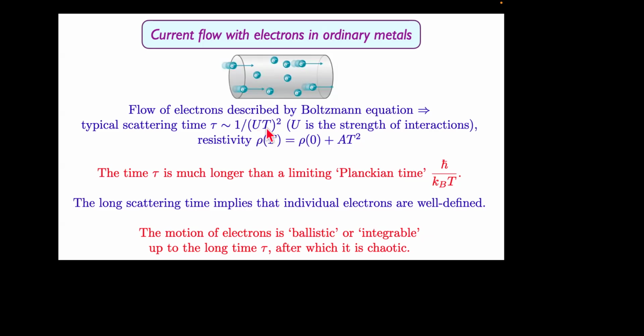It diverges as temperature goes to 0. So it becomes very long as the temperature becomes smaller and smaller. And one consequence of this is that the resistance of a metal increases as temperature squared. Okay, now suppose I increase the strength of the interactions, which is U here, then this time becomes shorter and shorter because the collisions become more and more often. And then at some point, this has to break down, or should it?